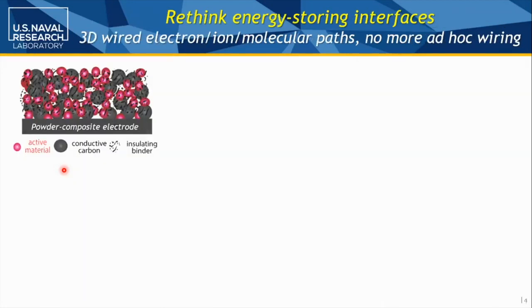So our way to classically make an energy storing two-terminal device, regardless of what the materials are or the electrolyte, is you've typically got an active material in red here that's not a great electron conductor. You mix it in with something that helps you move an electron, so to call it an ad hoc electron wire, which is typically a conductive carbon powder. And to keep those powders together, you often have to put in polymer binders.